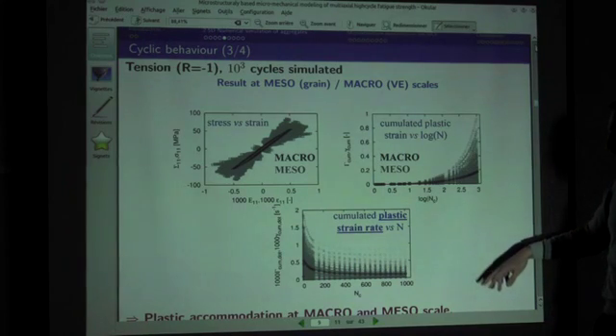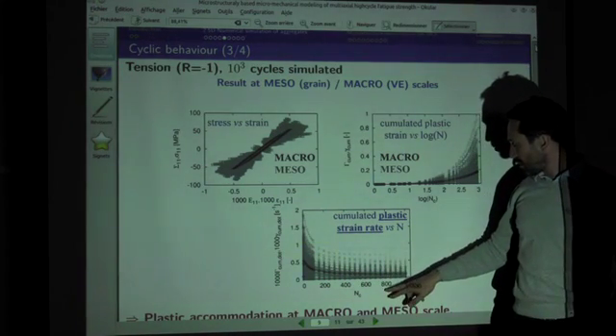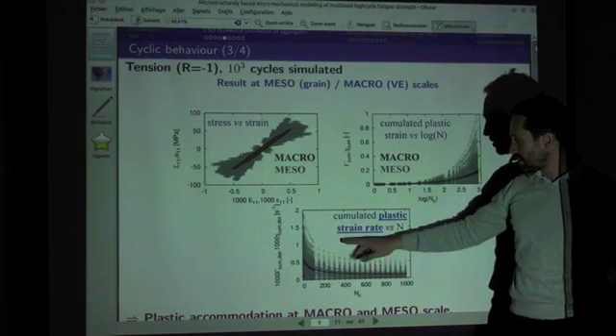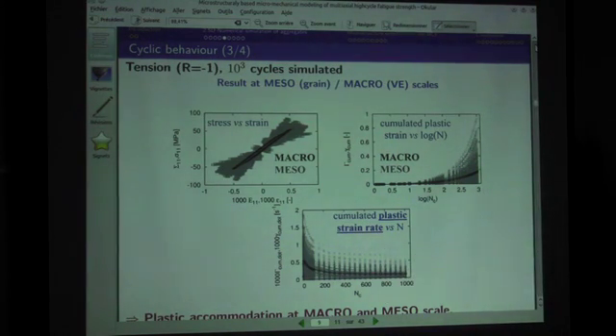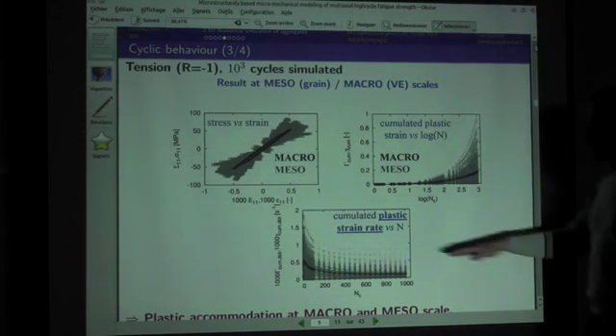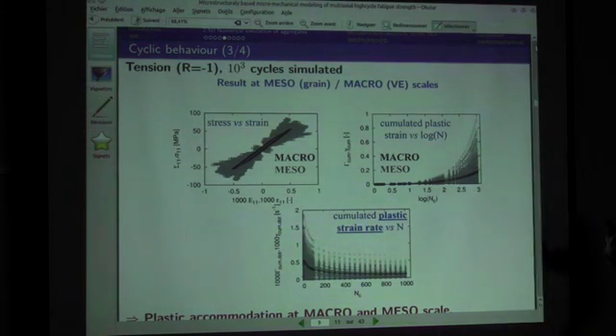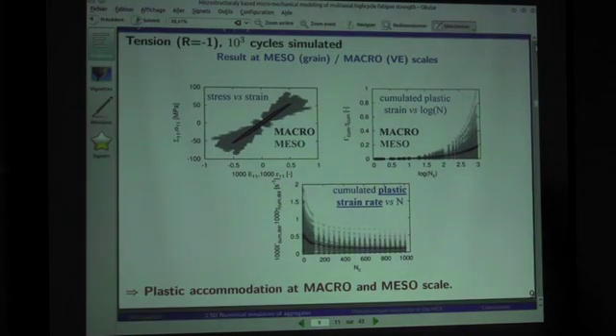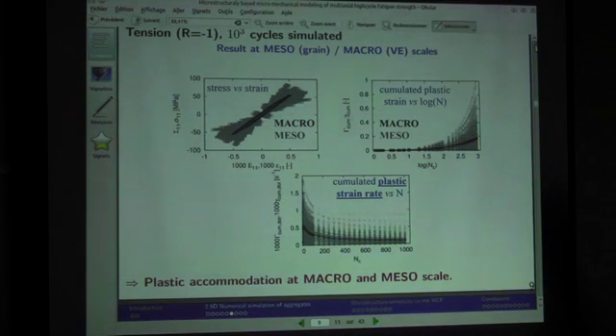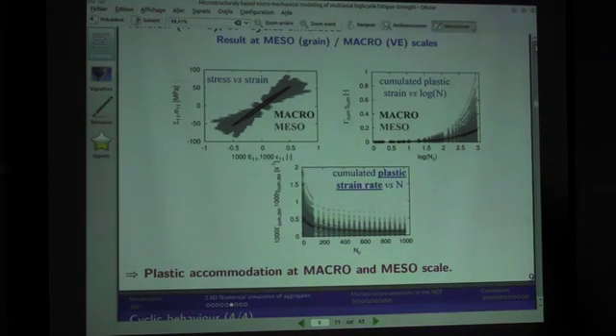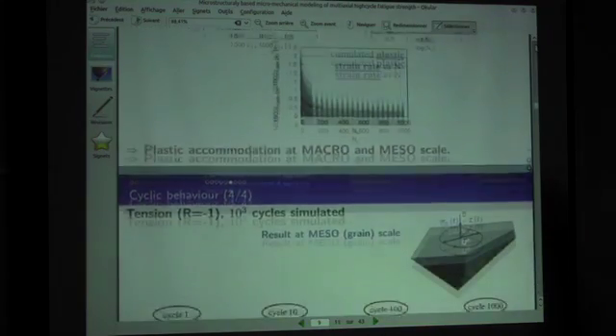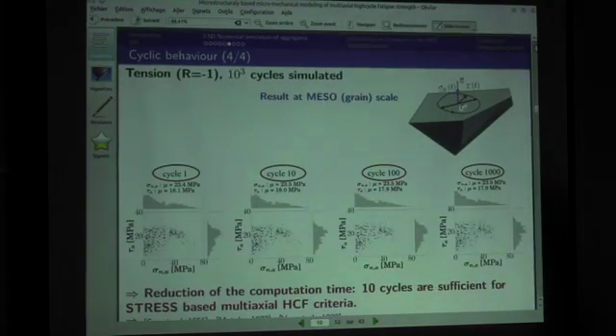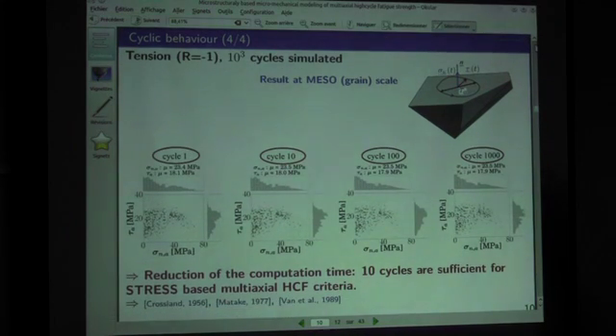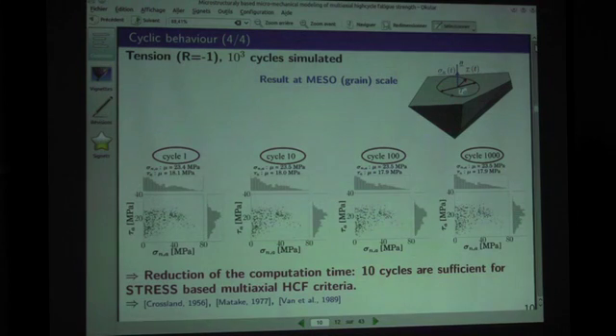And what is interesting here is that you need more or less 1,000 cycles, a bit less, to stabilize completely your strain rate, your plastic strain rate. So it means that if you want stabilized pictures in terms of strain, you need much more time than if you use the stress data. So that's one of the reasons why we have been using in the first approach mostly stress-based parameters, and I will not show you what we've been doing in terms of strain-based parameters.